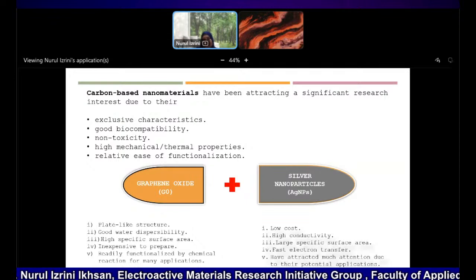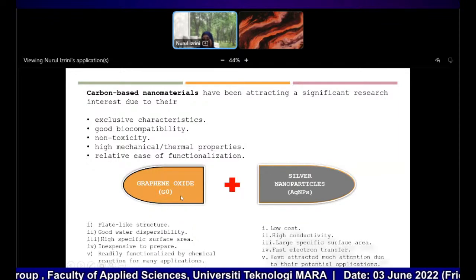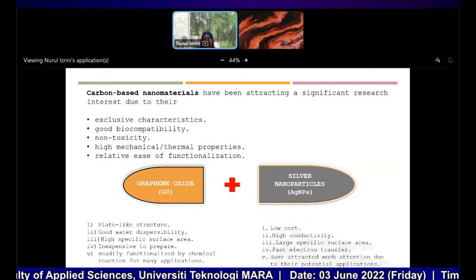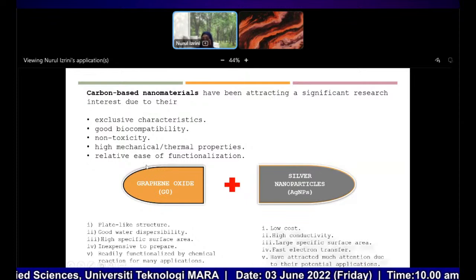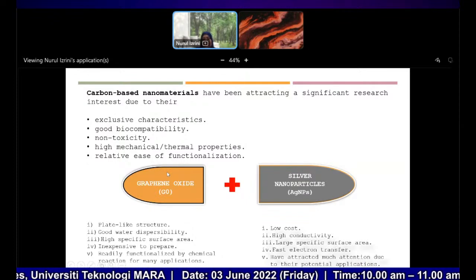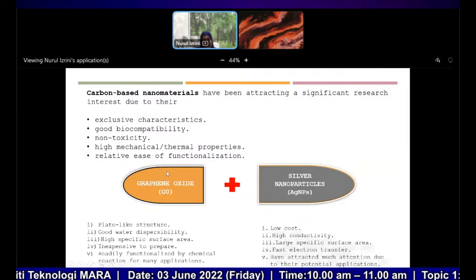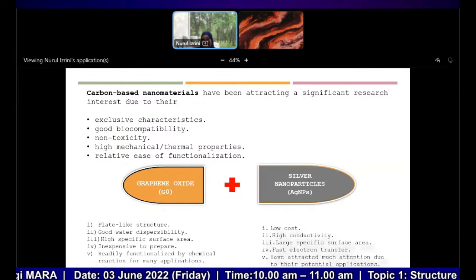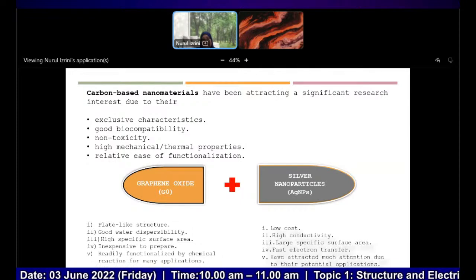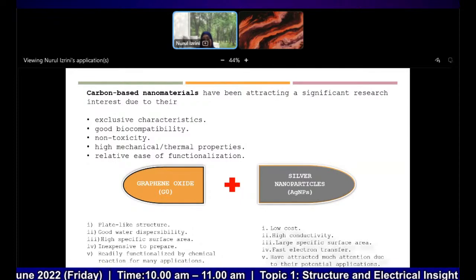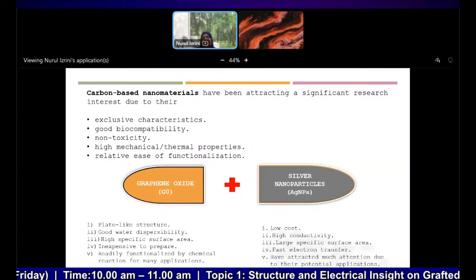This makes sense to use this kind of material as a substrate for the deposition of inorganic nanoparticles like silver, gold, copper, palladium, iron, cobalt, etc. The hydrophilicity and exfoliation of graphene oxide have offered exciting opportunities to build nanocomposites or nanohybrids and to form strong physical interactions with small molecules and polymers. Besides that, graphene oxide also has abundant oxygen-containing functional groups like epoxy, carbonyl, carboxyl, and hydroxyl, which allow the creation of the perfect surface to anchor inorganic nanoparticles for enhanced wider applications.